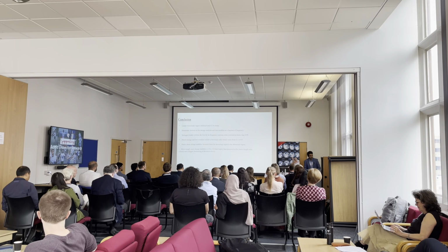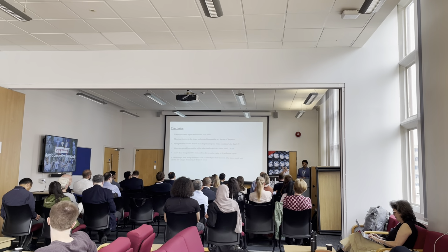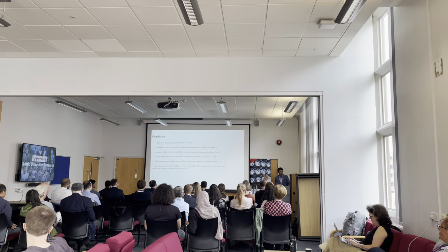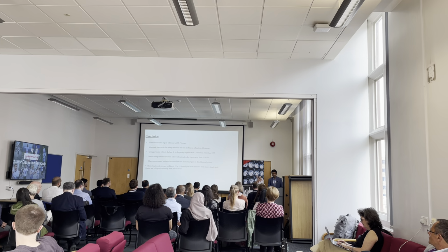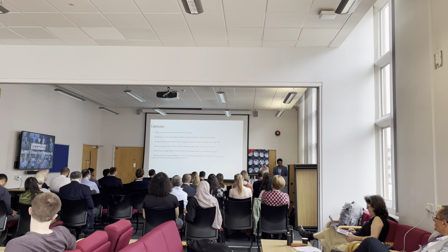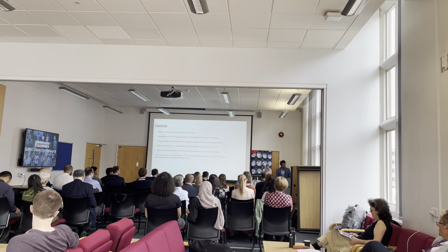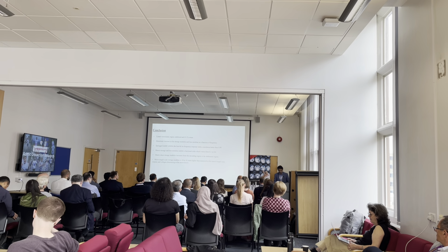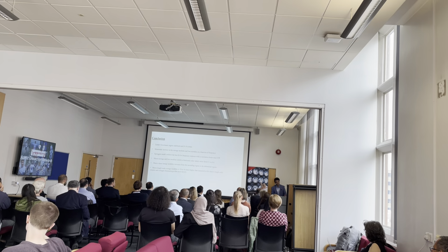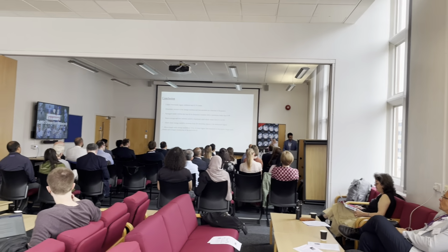Then the interesting part was that for the storage modulus and loss modulus at the macro length scale, we observed a behavior which was different in terms of the dependency on frequency, as in some regions were more dependent on the frequency compared to other regions which were slightly less dependent on the frequency. So it went from 0.1 to 0.6. And then the macro shear storage modulus increases from the ascending region to the abdominal region, and the same is also valid for the micro scale storage modulus.